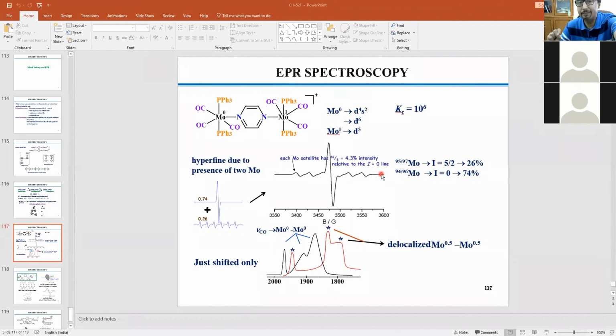If one moly interacts, that means the other moly is not coming into the picture, so it will be a localized scenario. Now, if you got 11 lines, that means 2 times 5/2 plus 2 times 5/2 plus 1, that is 11. That means this unpaired electron is shuttling between this moly and this moly via the mediation of these orbitals. And that is possible if they are energetically compatible. That means moly, bridge and moly, all 3 are energetically and symmetrically compatible. Even then, if your distance increases too much, this delocalization is not possible. If the distance is reasonable, and the orbitals are energetically and symmetry-wise compatible, then one could anticipate it. So what I mean is, if it is localized as it is written over here, then this electron would only interact with the nuclear spin of this moly.